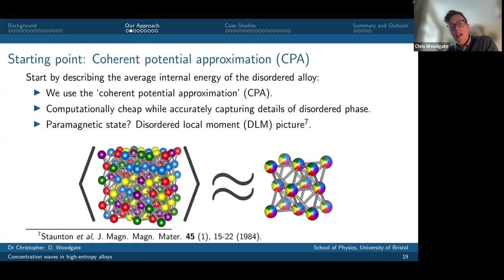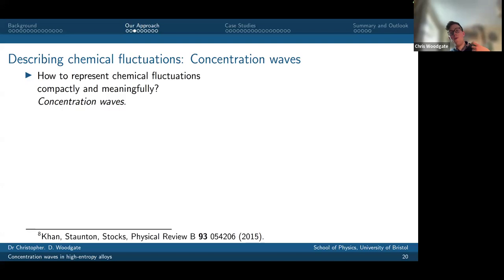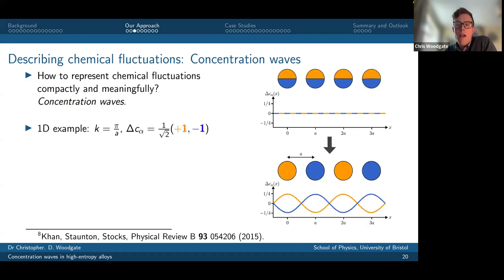Okay, so the coherent potential approximation gives us a means by which to describe the homogeneous disordered alloy, right? So if you like the infinite temperature limit of a solid solution where there are no chemical fluctuations, no chemical correlations whatsoever. But we want to look at phase stability, which means we need to describe local chemical fluctuations. And the way we do that is using concentration waves. Okay, so this is a means by which to describe how these partial lattice site occupancies in my CPA effective medium are varying. Okay, so here's a 1D example of a concentration wave, okay, in a binary 50-50 alloy.